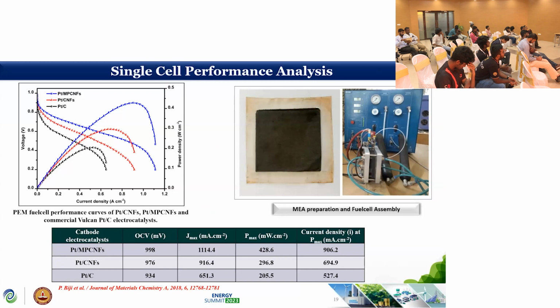And after analyzing all the properties, we attempted the fabrication of MEA. We did the MEA fabrication, then single cell assembly was done, and the polarization curves were measured. We could see that the maximum power density obtained for the mesoporous carbon nanofibers was somewhere around 428 milliwatts per centimeter square. It was almost double the performance of the commercial Pt/C.